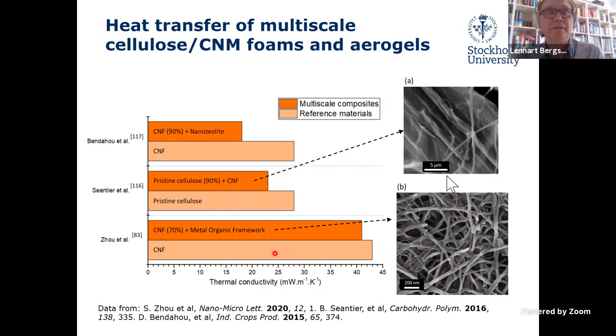And here you have CNF mixed with metal organic frameworks. You see in all these cases, even putting in a relatively minor amount of the additional material, you have a reduction in the thermal conductivity, which is probably related to the formation of heterogeneous interfaces and the phonon scattering occurring at those interfaces.